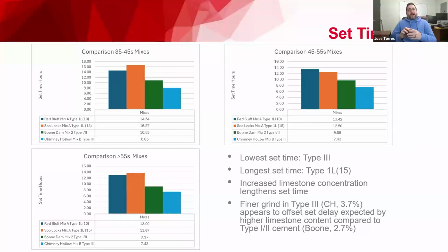So here we're comparing set times. In the 35 to 45 second range, basically the 1L15 took the longest to set - it's colored in orange here. And the type 3 took the shortest amount of time to set in the 35 to 45 second range. When we get to the 45 to 55 range, our 1L10 seemed to take the longest, and again type 3 was the shortest time. And then greater than 55 seconds, we're back to the 1L15 having the highest set time, and again the winner, type 3, setting faster.